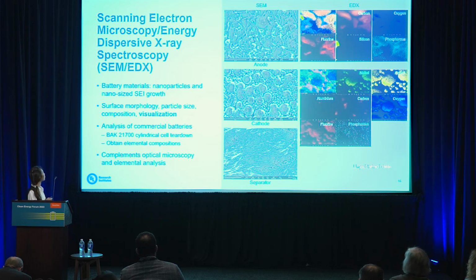Similarly, it provides information on surface morphology, particle size, composition, and really is a very good visualization tool. On the right here, this is some in-house unpublished data that we've done on commercial batteries. We did a teardown of the BAK 21700 cylindrical cells. You can see that we performed SEM on the anode and the cathode, and we can see some elemental composition coming from the anode and cathode. It's also interesting to look at the separator. You can see how porous the separator is.